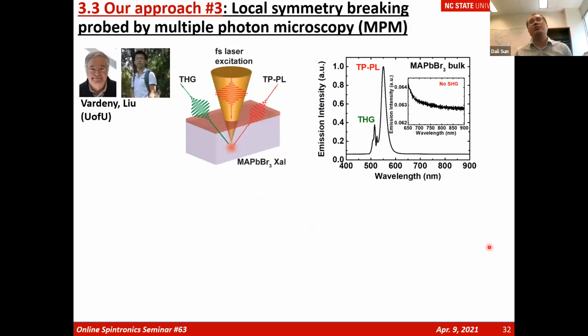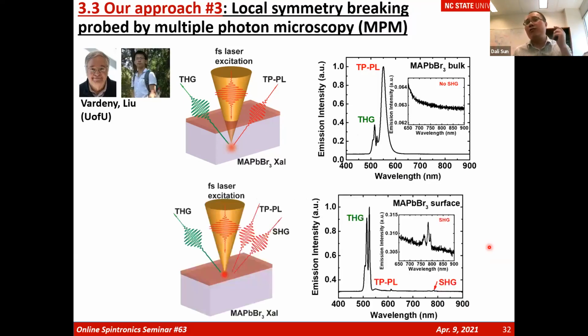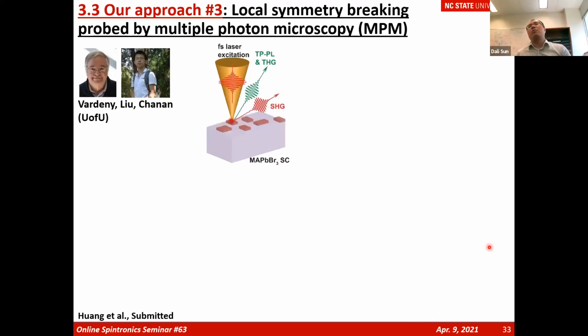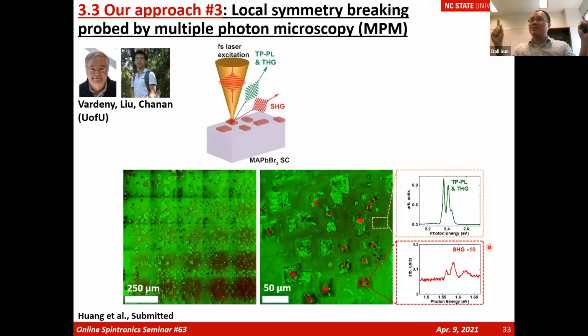That's the reason we asked the University of Utah Valy Vardeny's group to do the second harmonic generation measurement. Second harmonic generation, SHG, is a multi-photon microscope to determine the crystal symmetry. If you focus the laser into the bulk of a single crystal, you will only observe third harmonic generation. It's indicating there's no symmetry breaking. Only when you're focusing on the surface, you can see second harmonic generation due to the absence of inversion symmetry, but a very weak signal.